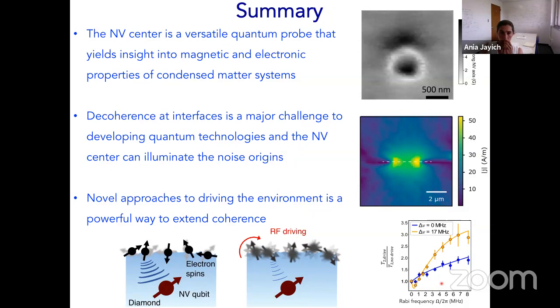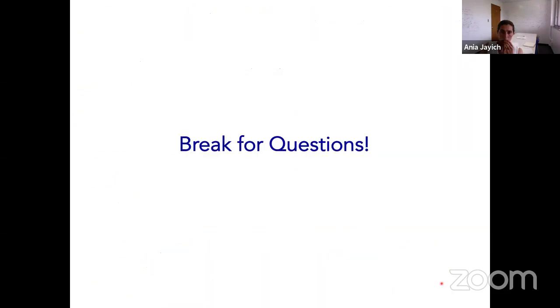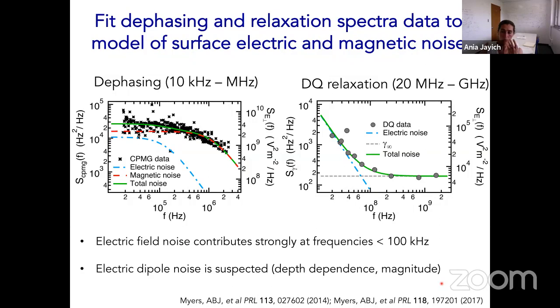If I were to give one thing, we've been able to discriminate sources of electric field induced decoherence and magnetic field decoherence using, again, near surface NV centers under the surfaces that we've prepared. We're able to largely decouple electric field noise if our dynamical decoupling is fast enough to decouple up to 100 kilohertz, because electric field noise seems to contribute strongly at low frequency. So in this specific example of NV centers about 10 nanometers below the surface, we're able to decouple most of the effects of electric field, but not all the effects of the magnetic field.